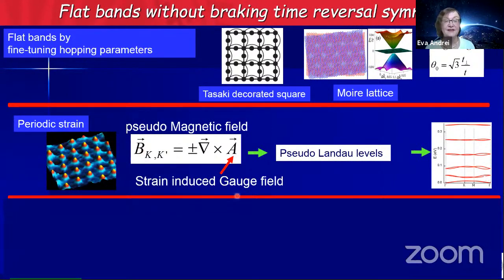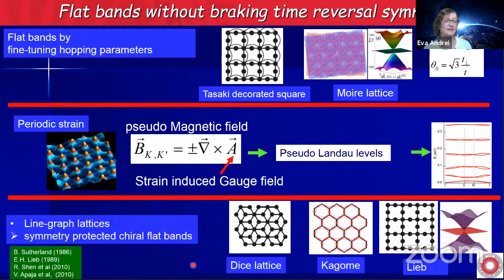So that gives us a strain-induced gauge field, which gives you pseudo-Landau levels, flat bands, without breaking time reversal symmetry. If I have time, I'm going to tell you about this as well. And the third way of doing it is line graph lattices, that naturally have geometrically induced flat bands. These are the Kagome, the dice lattice, the Lieb lattice, and there are many more. And then you get a destructive interference between wave function tunneling between nearest neighbors, between corner and lines here. So then you get flat bands that coexist with non-flat bands, with Dirac cones, essentially.